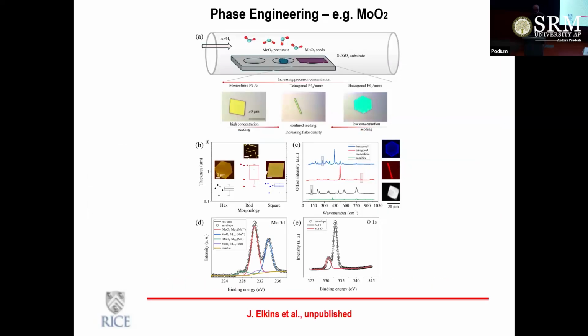Now, when you're trying to grow such materials, there are also some challenges because many of these materials exist in multiple phases. When we talked about nanotubes, we said there are metallic nanotubes, there are semiconducting nanotubes. It's a very similar story here. And because they are going to the atomically thin regime, it can very easily change the structure, maybe distortions and things like that, and that can easily change the phase.